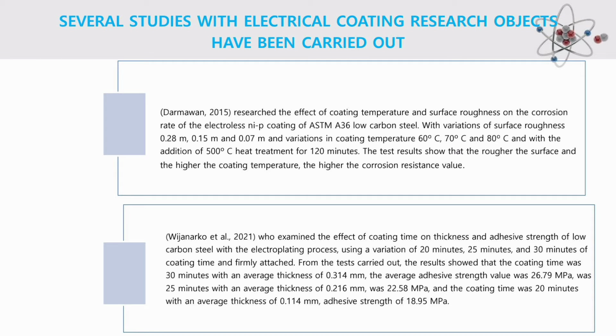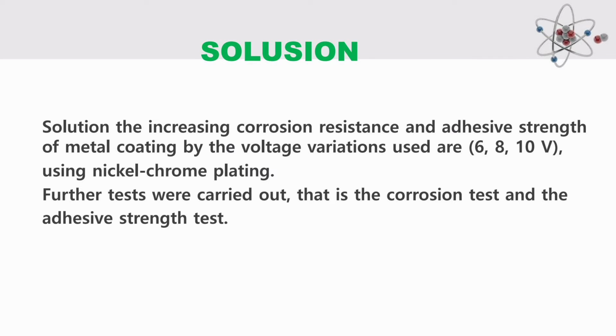Wijanarko et al. 2021 examined the effect of coating time on thickness and adhesive strength of low carbon steel with the electroplating process, using a variation of 20 minutes, 25 minutes, and 30 minutes of coating time. From the test carried out, the result showed that the coating time of 30 minutes with an average thickness of 0.314 mm had an average adhesive strength value of 26.79 megapascal, 25 minutes with an average thickness of 0.216 mm was 22.58 megapascal, and the coating time of 20 minutes with an average thickness of 0.114 mm had adhesive strength of 18.95 megapascal.